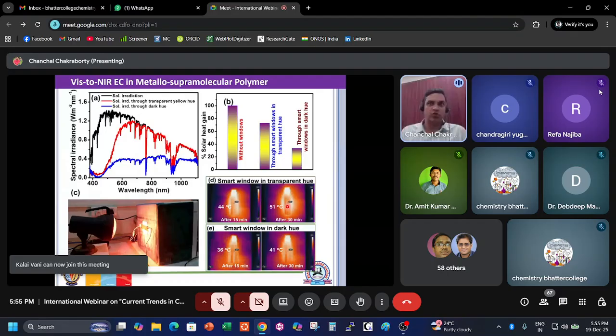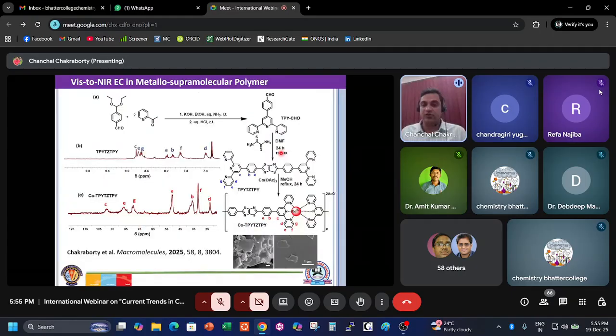We find that this color is brownish black. The brown color probably comes from the thiazole part, and this conjugated organic ligand can give some kind of color. That is why we started this work, so that we can cut down the organic part in the complex. So we developed another complex where the organic ligand size is very small.